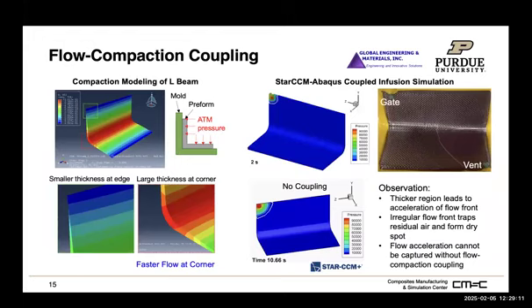As you will see while we look at the entire simulation workflow, we are really focusing on the integration. One of the things we realized is that we see so many defects during our infusion, even with something as simple as a rectangular bracket shape. You would think it is easy: we have the resin infused on one end and sucked out on the other end, and we expect a very smooth flow, as indicated in the original simulation, where the white line shows the movement of the resin flow front. So we do expect to see pretty smooth behavior.